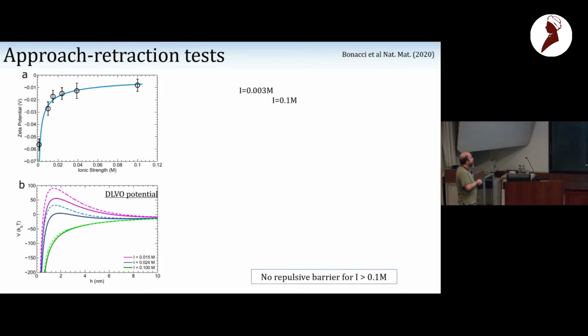But in fact, now we can take our system, we measure the charges of our particles. I'm sorry, there are movies that will not show up. But basically, if we reconstruct the DLVO potential, depending on the ionic strength of the suspension, we can very easily, and for very reasonable values of the ionic strength, be in a situation where particles